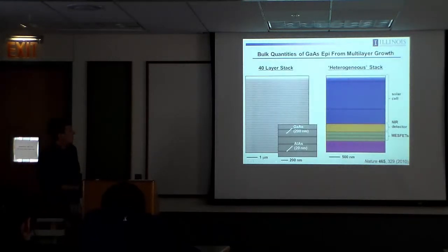And you can do this quite well. We work with Xiuling Li here in electrical engineering. There's the 40-layer stack, gallium arsenide 200 nanometers thick, aluminum arsenide sacrificial interlayers, again, 20 nanometers thick, etch down, eliminate the aluminum arsenide, lift off a lot of gallium arsenide nano membranes.